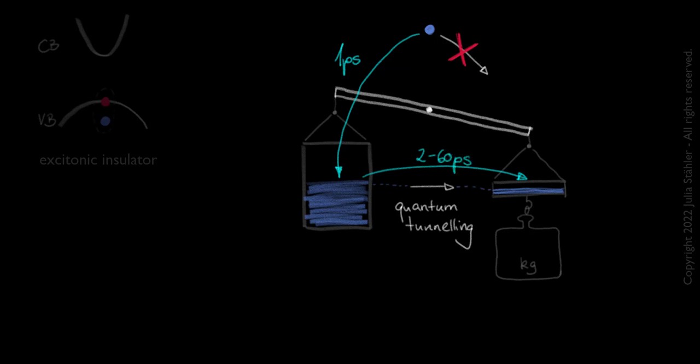The exact time constant of this process depends on several conditions: the sample temperature and excitation density, which means the number of excited electrons in the laser spot. The reason is that the quantum tunneling may occur in both directions, forward and backward, and is thermally activated.